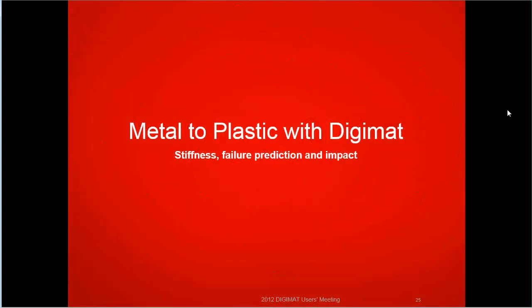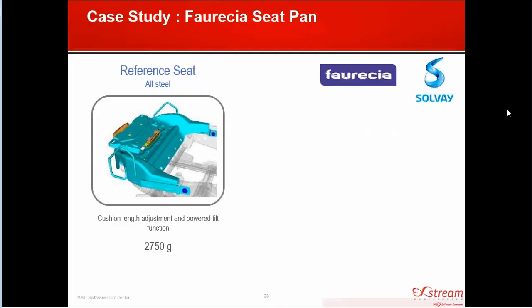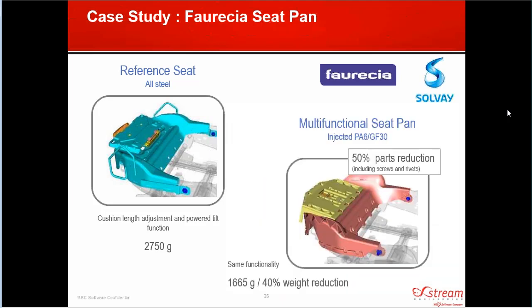One more case study here, and then I'm going to wrap things up and open up for questions. This case study is a metal to plastic design comparison, really looking at stiffness and failure prediction for an impact scenario. The case study was done by Faurecia with Solvay. Solvay is one of our material supplier partners, and they were trying to take a reference seat, which was made from all steel, and convert that into a seat pan made of nylon reinforced with 30% glass fiber. Using Digimat in the design process, they were able to get a 50% reduction in the number of parts and a 40% reduction in the overall weight with the same functionality, going from the steel seat pan over to the nylon reinforced with glass fiber seat pan.